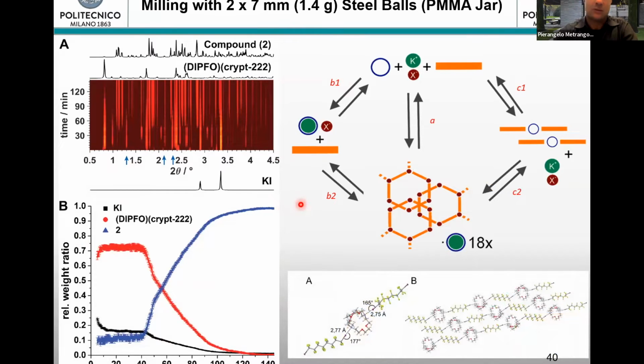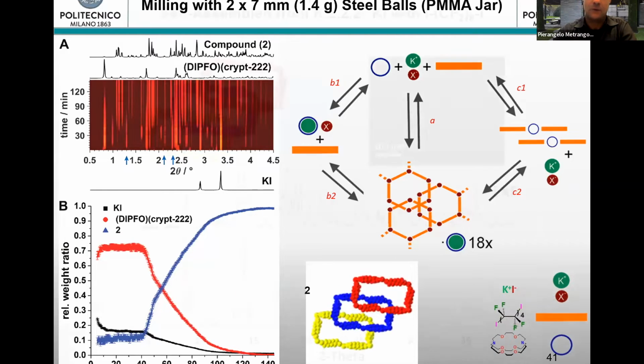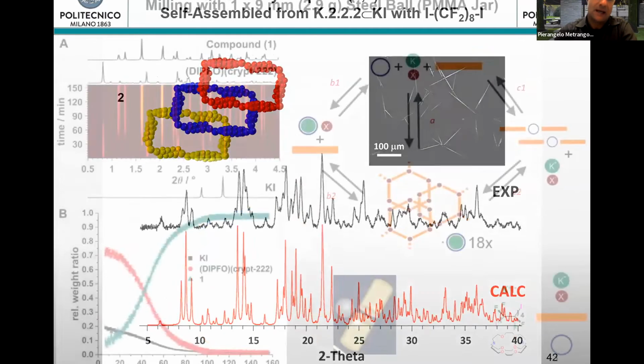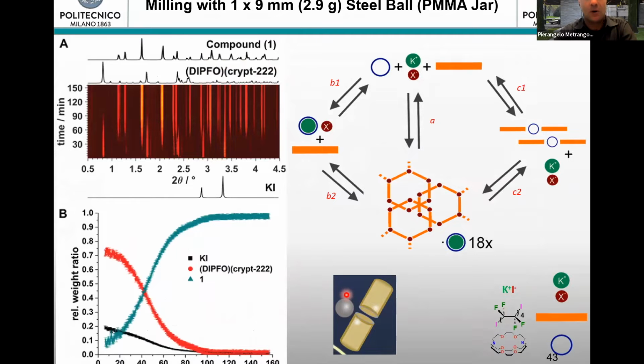Obviously, we were also able to report the intermediate that we were getting, which is a neutral co-crystal where the cryptofix is coordinating the diiodoperfluoroalkane, but this intermediate disappears very soon in order to get the three-component system. But if you mix the two components in a ball mill using a single ball with much more energy, the intermediate converts very, very fast to the Borromean ring structure. So it is surprising to me to see that this very complex topology can be obtained directly in the solid state, and we can control the obtainment of one polymorph or the other simply by changing the milling conditions.